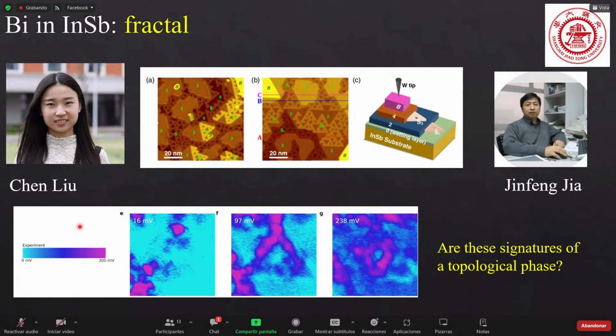So now about the physics and the bismuth. The first thing is that, at least to the best of my knowledge, bismuth in indium antimonide is the first example where we really saw these fractal flakes. So by itself, I think it's quite important. I don't know so much about ab initio methods to understand exactly if you change bismuth by a different material, how we can actually obtain the same physics for the structure itself. But for us, the main important point of bismuth is that it has a very high